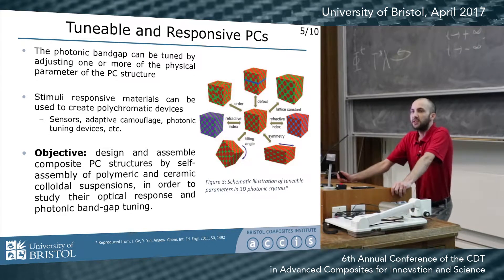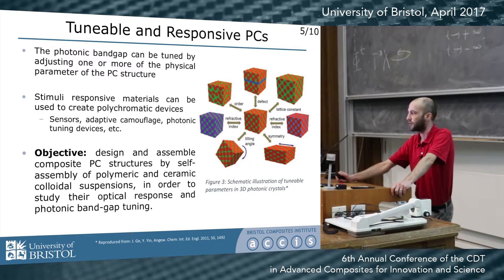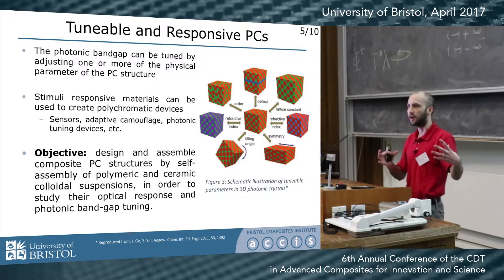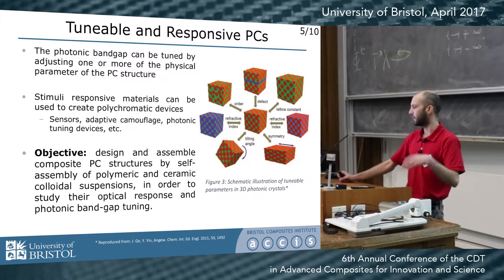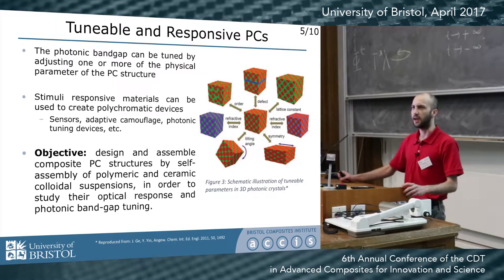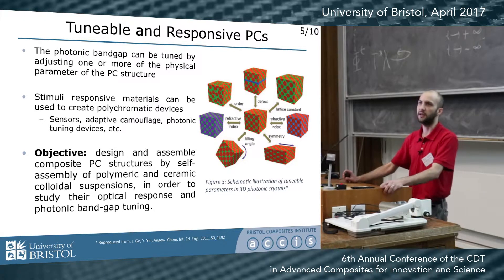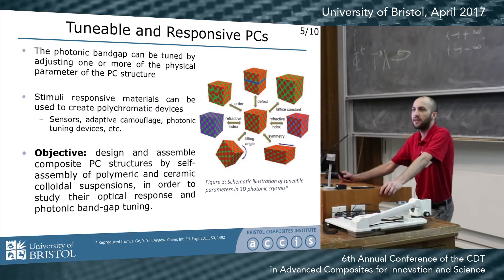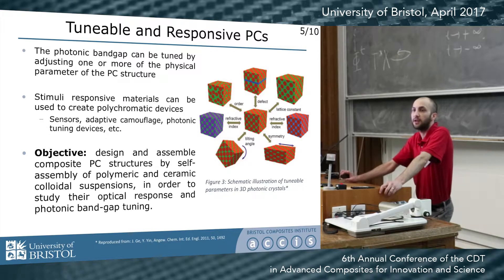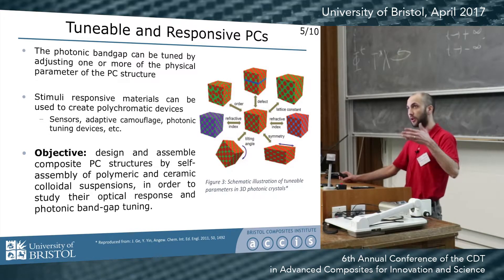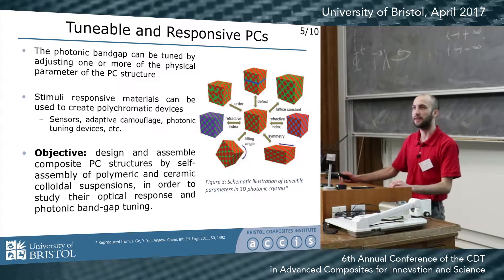The color and optical properties of these materials depend on physical parameters of the structure, such as the lattice spacing, the size of the periodic structure, the refractive index contrast between the two different phases, and also the degree of symmetry and order in the structure. The objective of this project is to design and assemble composite photonic crystals in order to study and tune these optical properties.